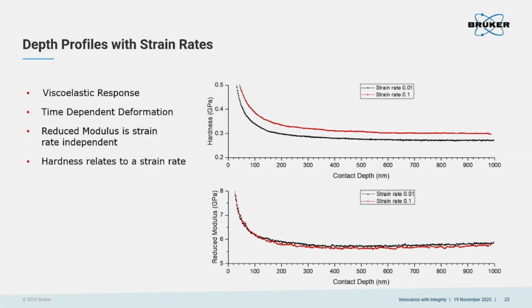So you can see that with the same probe, the same penetration depth, if we use a higher speed, a higher strain rate, the hardness will be higher. And if we use a lower speed, a smaller strain rate, you will find the hardness will be lower. So hardness is highly sensitive to strain rate.